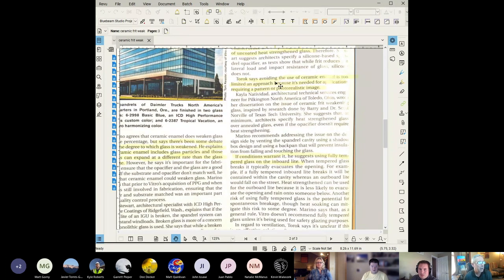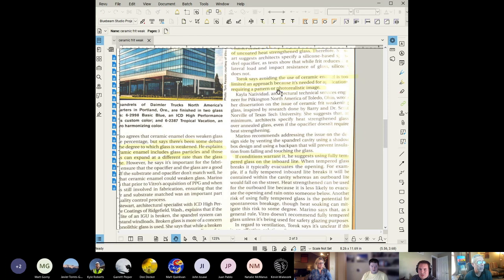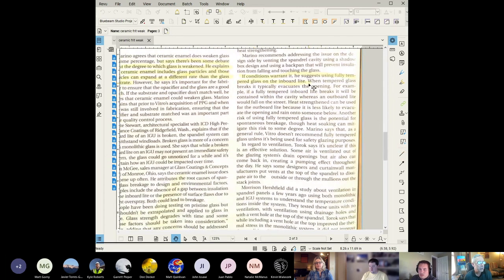Avoiding the use of ceramic enamel is too limited of an approach because it's needed for applications requiring a pattern or photorealistic image. We're probably going to see a lot more of this because architects are wanting to do more with patterns and photos in the glass insulated glass units. If conditions warrant it, he suggests using fully tempered glass on the inboard light. For most spandrel glass we should have tempered anyway just out of the concerns associated with thermal expansion. Make sure that we have tempered glass specified on both pieces of glass if it's a spandrel unit.